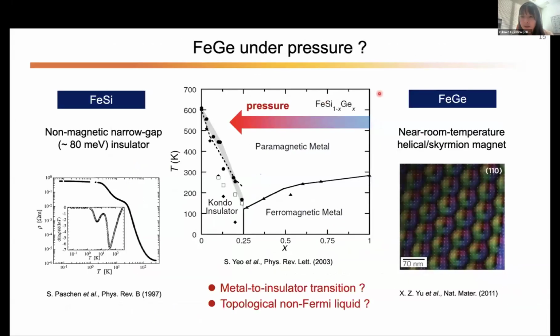So motivated by these works, we have decided to try similar experiments in iron germanium, which has the same crystal structure, but a very high transition temperature, and it's very famous for the skyrmion formation near room temperature. And if we apply pressure to this iron germanium, the system will be effectively tuned to iron silicide because of the lattice change, if we consider the chemical pressure between silicon and germanium. And this iron silicide is another very famous compound, which is known as a non-magnetic narrow gap semiconductor with very strong electron correlation.